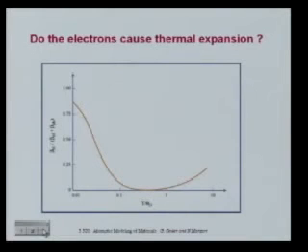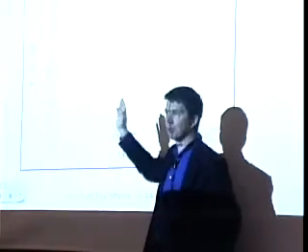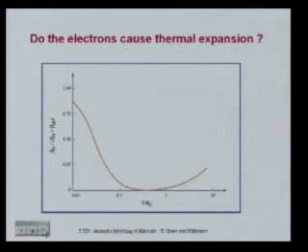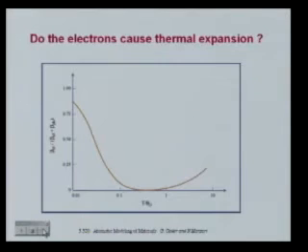So the electronic one plays an important role, but all of them together are small anyway. And here, this is a logarithmic scale, so let's say roughly half of the Debye temperature, the electronic effect is almost meaningless. That doesn't mean there are not some esoteric materials where it does become important. There are some materials, typically complex oxides, where you can start inducing valence fluctuations at elevated temperature, even 300-400 Kelvin. And in oxides, if you change the valence of an ion, they change size because the orbitals are very localized. So there you can see a substantial effect of electrons on thermal expansion. But in many cases, we wouldn't worry about it.